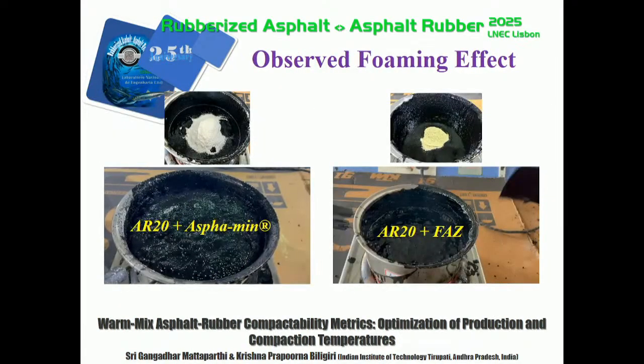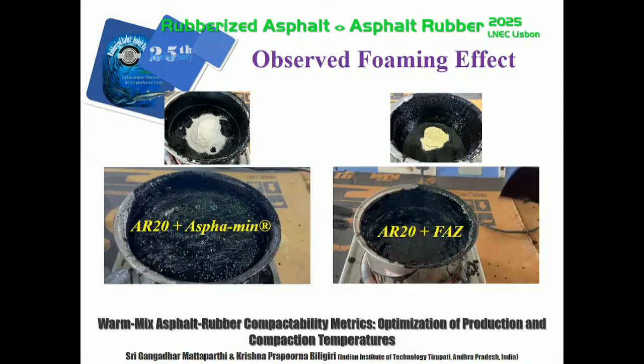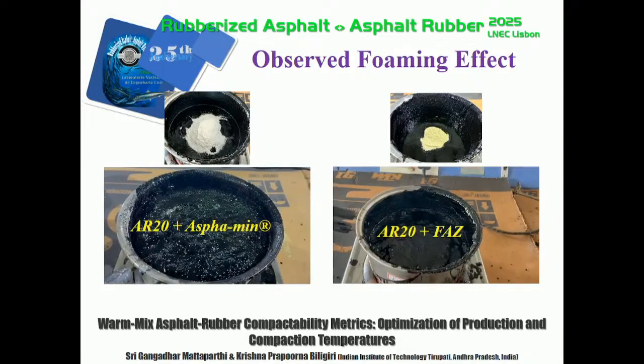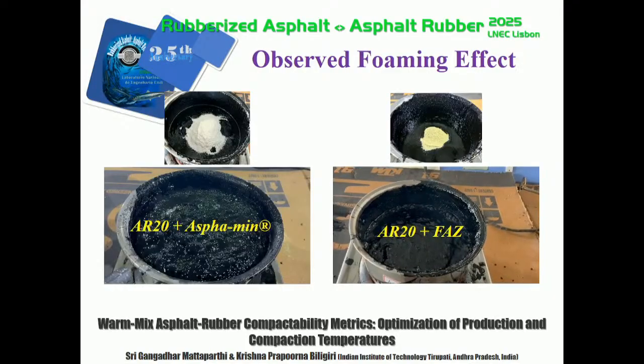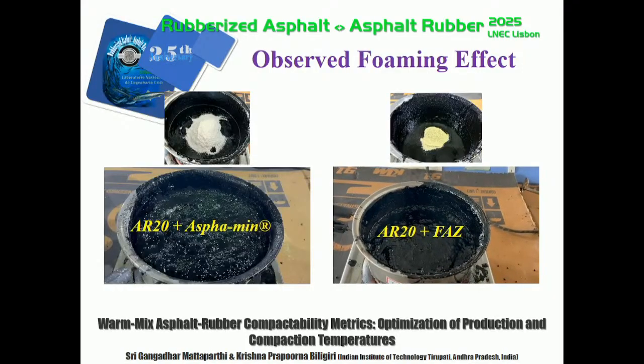As you can see, the foaming effect observed with the asphalt binder when we added the zeolite, there is water that is foaming, and this helped reduce the viscosity temporarily and the production temperatures as well.